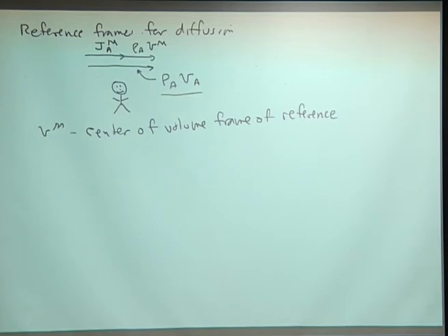Center volume frame of reference. And what that means is that it's a marker frame such that the total volume of the system is equal to 0. The way to really put this is that the partial molar volumes of A and B are equal. And if you think about this in terms of a crystal rather than a fluid, it says that the vacancy concentration is always at equilibrium.